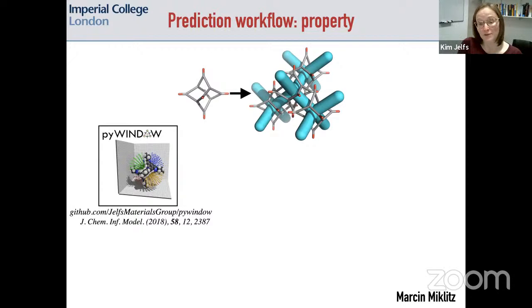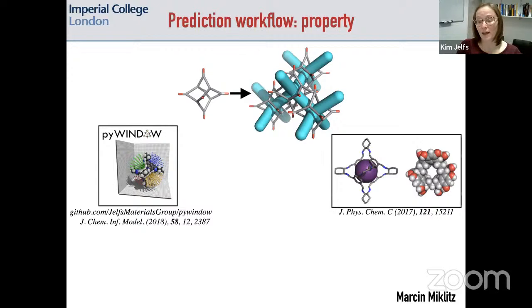Right, so we have pyWINDOW for analysis of the structure, and we took this forward with looking for xenon-krypton separation candidates from previously reported porous molecular systems that were in the literature. We took about 200 of them from the Cambridge Structural Database and revisited them just by doing the analysis on the single molecule level for xenon-krypton separation, by doing that structural size analysis, by doing DFT calculations, looking at the binding energies of the xenon-krypton, and also by doing metadynamics simulations that gave us insight into the barriers for removing xenon and krypton through the window of the cage. So it would be important for a kinetic-based separation.